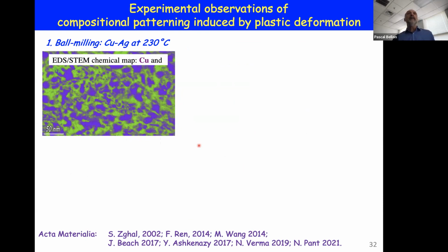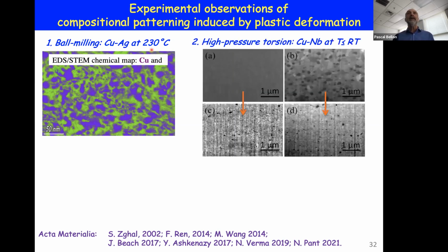Here's an image of a nanocomposite of copper and silver synthesized by ball milling at an intermediate temperature. Just like under radiation, if you ball mill at low temperature or cryo temperature, disordering and mixing take place and you have a solid solution. If you ball mill at too high a temperature, silver and copper phases coarsen. But here at this intermediate temperature, they reach a steady state size. On the right-hand side is a more reactive system, copper-niobium, where the niobium precipitates show up as dark regions in SEM in secondary electron mode.